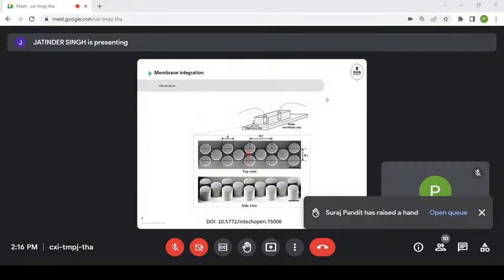Another thing instead of a membrane we could do is actually microfabricate a filter. Normally we know our filters as a crisscross of cellulose if it's a paper-based filter. You can also mimic that structure in a much more regular way by making pillars. If you would do solid phase extraction in this, for example, all these pillars add to the surface area that we've got available in our microchannel. The smaller the channels, the smaller the pillars, the higher the surface area, the more effective it will be working as a chromatographic phase. And I know that there are some activities going on at the moment using two-photon lithography for printing chromatography columns, because you can get very precise and accurate flow, because you can tailor a lot of your dispersion away through the way that you shape your pillars.